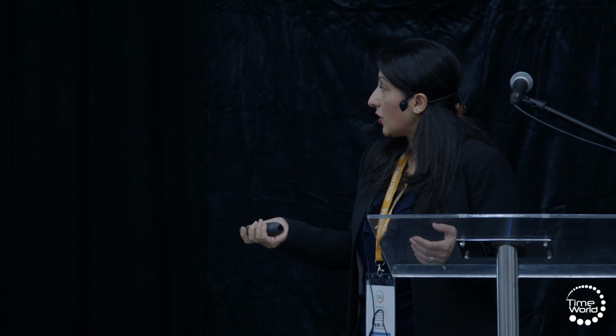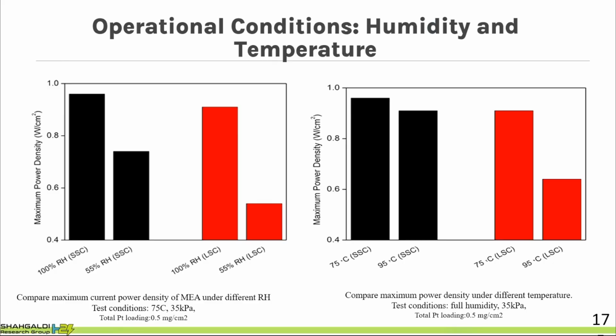The other thing that we tried in the lab is, if we are using different membranes like ionomer, what kind of operational condition is suitable for each type of membrane that we are selecting? So we find that if we are using shorter side chain ionomer, it stands higher temperature compared to the long side chain ionomer. Or if we have low humidity, dry condition, because we need to preserve the water near the three-phase boundary, it's better that we use shorter side chain ionomer compared to long side chain ionomer.